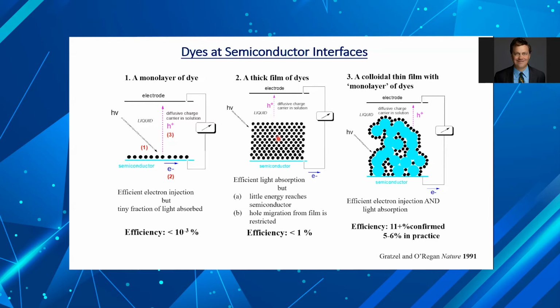It's very, very challenging. Well, it was in 1991 that Michael Grätzel and Brian O'Regan in Switzerland came up with a very novel idea. And that was, let's get rid of these planar electrode surfaces, single crystals or thin films, and instead use a very high surface area film. And initially these were just called colloidal films because the idea was to take colloidal nanoparticles and cast them in a film. Now we call them mesoporous nanocrystalline to really emphasize the importance of the mesoporosity.